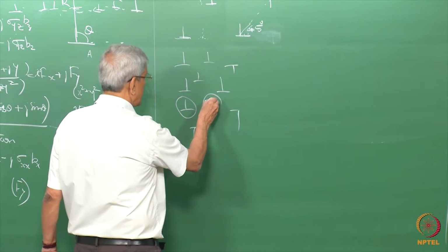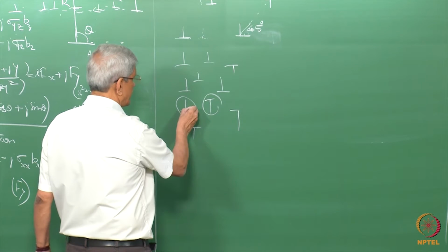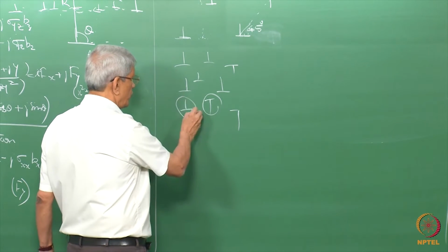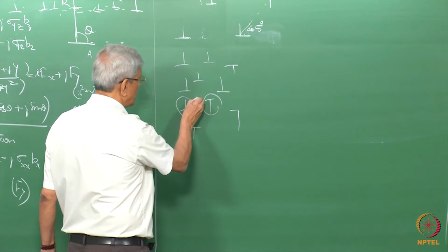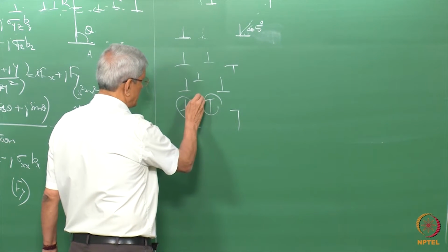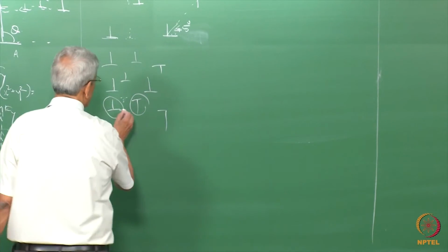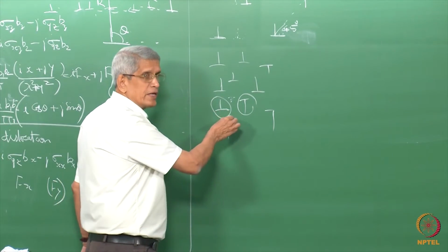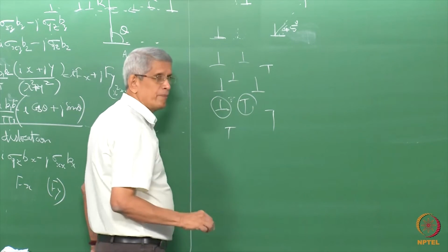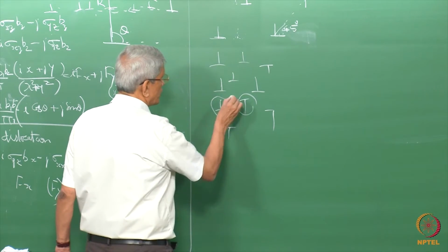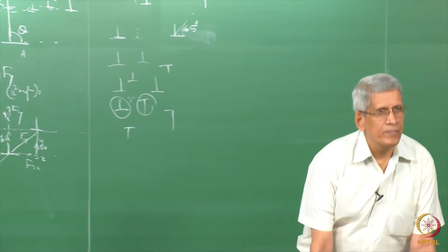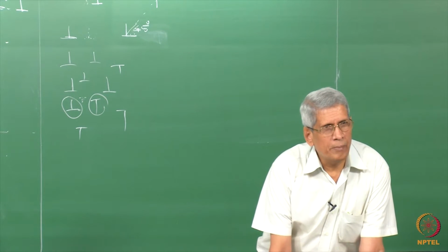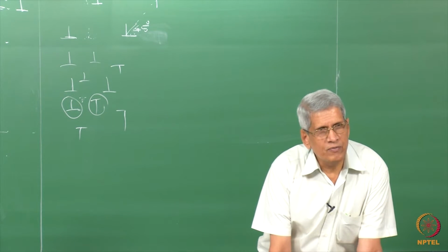Because of the glide force which is going to be there, these two come to a particular position, that is the minimum energy configuration which it will reach. Then the climb force can make the dislocation emit vacancies or absorb vacancies to climb up, and then these two can come together and cancel each other, correct. So, this is what will happen between dislocations with positive and negative Burgers vectors.